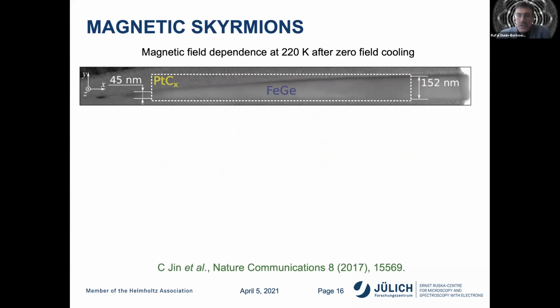So I'll start with an example which shows some work that we did a few years ago in 2017, where we patterned a crystallographically chiral material, iron germanium, into a long stripe. And this is representative of a magnetic track in which we may want to nucleate magnetic skyrmions, and we'd like to see how they travel along this track. So this track is 45 nanometers high on the left, 150 nanometers high on the right, and it's about 100 nanometers thick in the electron beam direction.